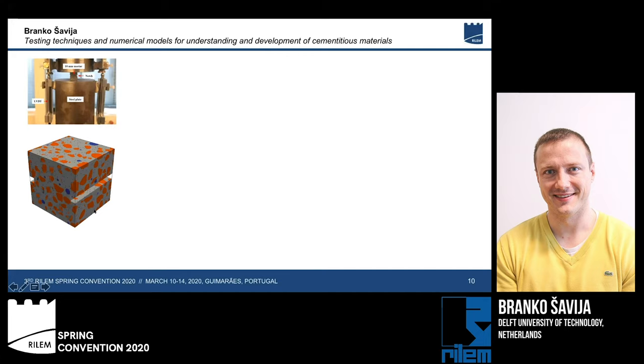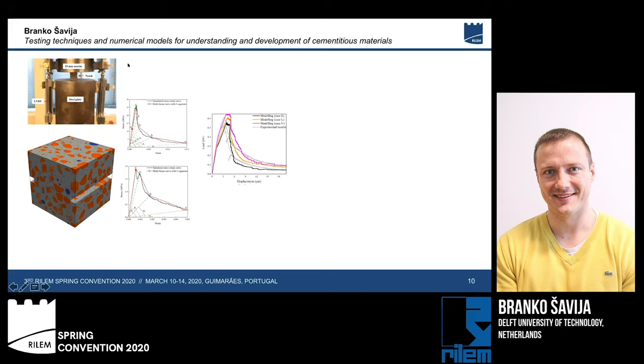We have in red sand particles, we have entrapped air, and we have in gray our hydrated cement paste. And from our microscale simulations, we know the constitutive relation for the cement paste, and we know the constitutive relation for the ITZ. For aggregates, we can assume that they are linear elastic. So we use these properties and then simulate the experiment at the higher scale. And we can see in this figure a comparison between our experimental results given in gray and our modeling results for three different assumptions. And actually, we have a very good match between our model and our experimental findings.